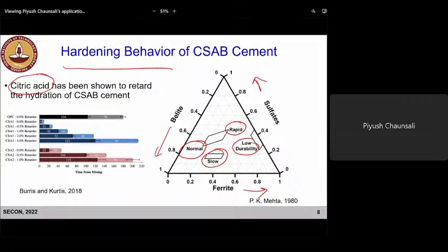And here you see the effect of retarder, in this case citric acid, on two types of CSA1, CSA2. And you see how the setting time was influenced by addition of citric acid. So citric acid has been shown to retard the hydration of CSAB cement. But more research is going on in looking at other admixtures also, which can be used to control the hardening behavior of CSAB cement.